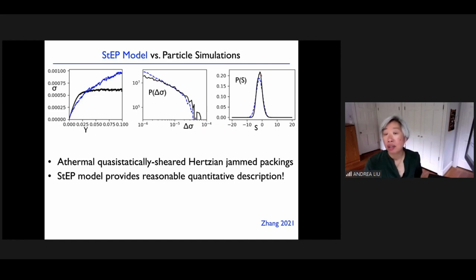And here's the distribution of softness, which, of course, as you're shearing it, that distribution evolves, and in steady state, it looks like this. Really very good agreement with the simulations. So the step model is really providing a reasonable description, not only a qualitative description, but a quantitative description.